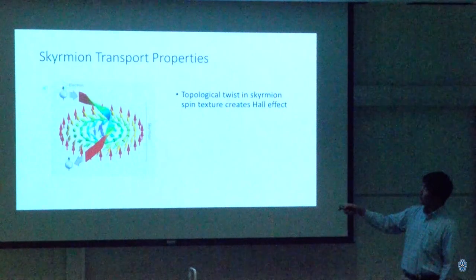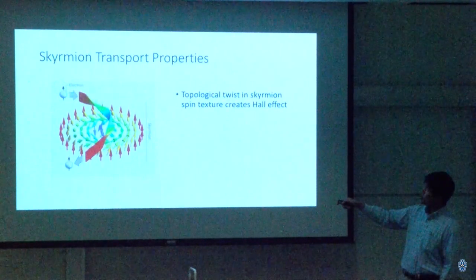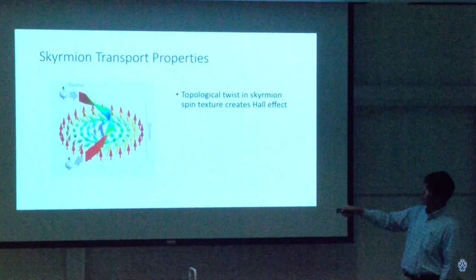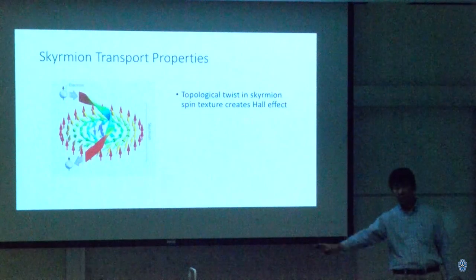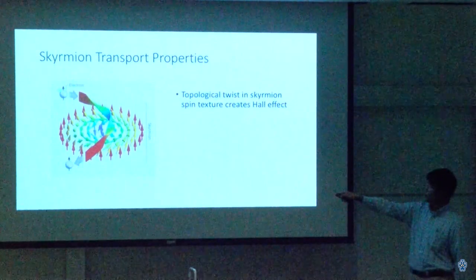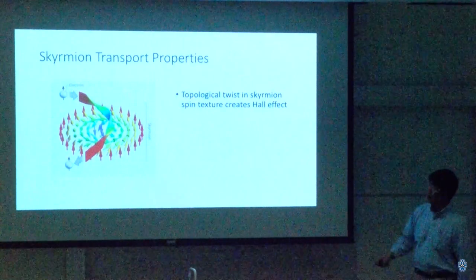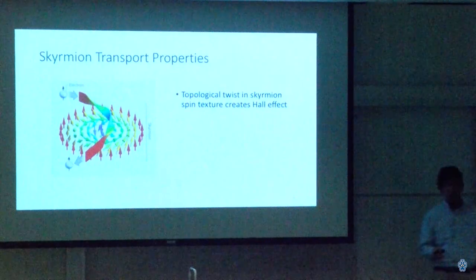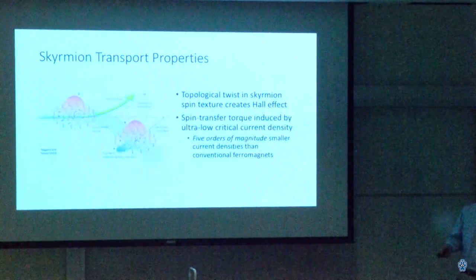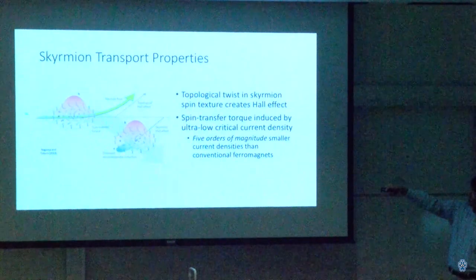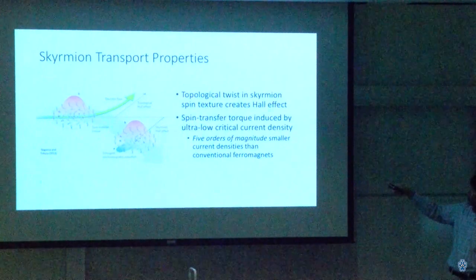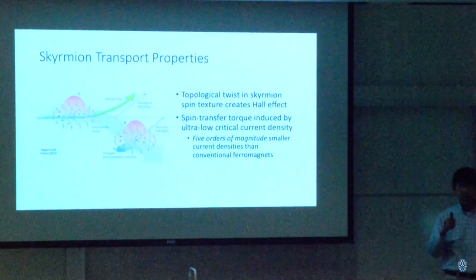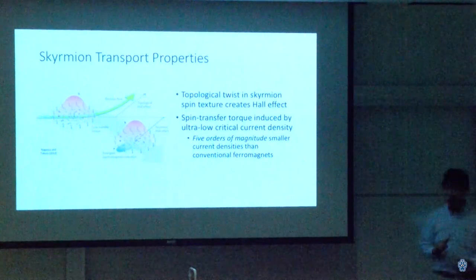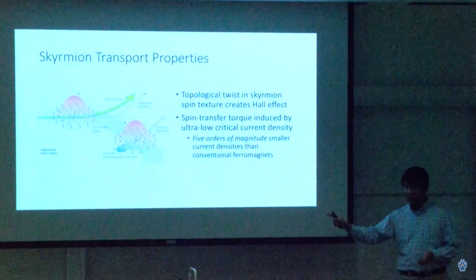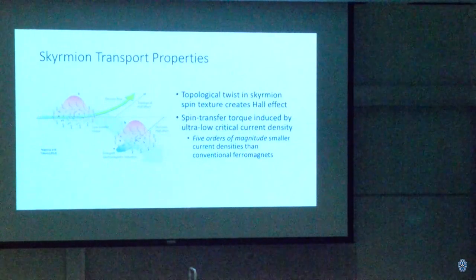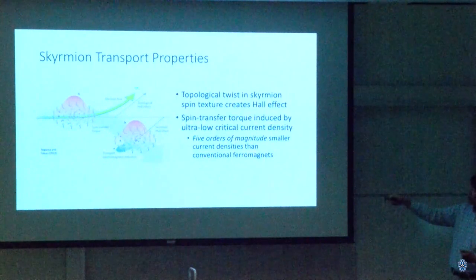And that's the case because the magnetic moment of an electron, as the electron moves through a skyrmion spin texture, has to continuously follow the spin texture of the skyrmion, and the spin as a result executes a full turn. Well, that turn ends up having the same effect as an effective magnetic field, and that causes the electrical current flow to deflect, causing the Hall effect associated particularly to the topology of the skyrmion spin texture. But at the same time, because you're conserving momentum, you're kicking electrical current in one direction, you're causing your skyrmions to also deflect in the other. So there is a topological Hall effect and a skyrmion Hall effect.